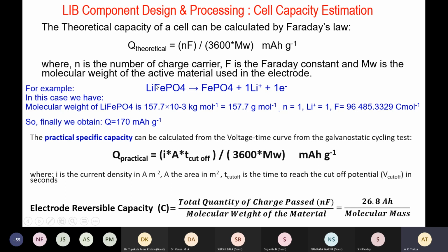For example, in the case of lithium iron phosphate, it undergoes a reaction theoretically, releasing one lithium ion, oxidation, and a stable FePO4 layered structure. So the molecular weight of lithium iron phosphate is 157.7 gram per mole, with N equal to 1 lithium ion taking part in redox activity, Faraday constant taken to be 96,500. The net theoretical capacity Q, when we put these values into the equation, works out to be 170 milliampere hour per gram.